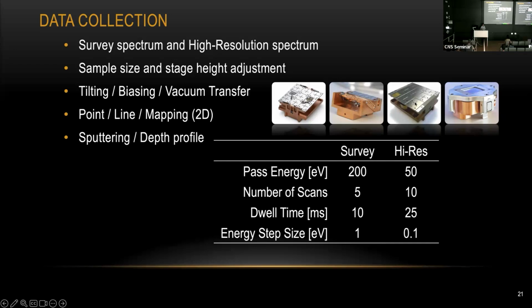The following stage here is called a biasing stage. The whole idea of using the biasing stage for XPS measurement is that you want to do work function measurement. And finally, the very last stage here is called a vacuum transfer module. That's for people who are working on samples that are air sensitive. For example, we have a lot of people working on lithium batteries here, and most of the time this material cannot see the air. So you want to load your sample on the stage in some kind of glove box vacuum environment and transfer the entire stage with your sample to the machine. So your sample won't see the air during the loading and unloading.